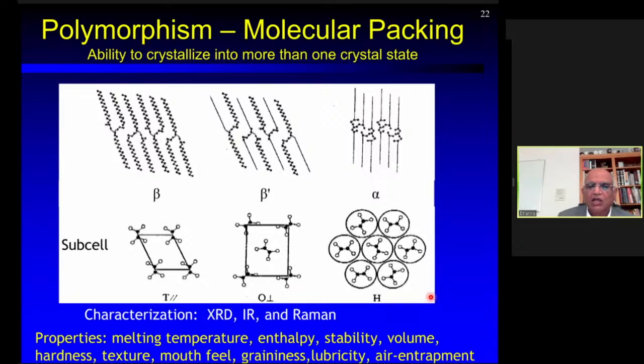However, if you look at the volume, because of the loose packing of the chains, alpha is the highest volume, beta is the lowest, and beta prime is the intermediate. Because of these different physical properties, the functional properties such as hardness, texture, mouthfeel, graininess, lubricity, and air entrapment capacity also